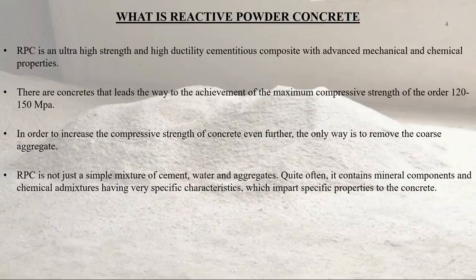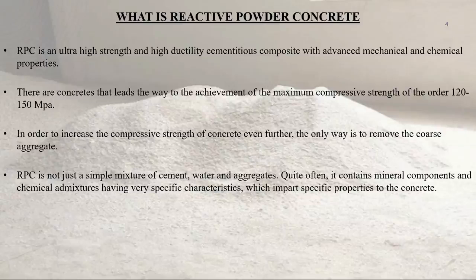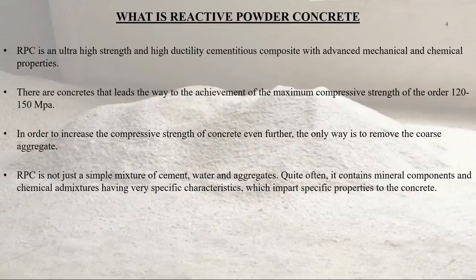Now the question arises, what is reactive powder concrete? RPC is an ultra-high strength and high ductility cementitious composite with advanced mechanical and chemical properties. There are concretes that lead the way to the achievement of maximum compressive strength of the order of 120 to 150 MPa. In order to increase the compressive strength even further, the only way is to remove the coarse aggregate. RPC is not just a simple mixture of cement, water and aggregate; quite often it contains mineral components and chemical admixtures having very specific characteristics which impart specific properties to the concrete.